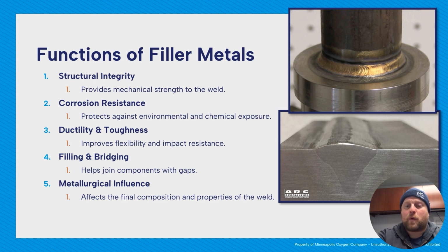Things like Cor-Ten or weathering steel, you have to use a particular type of filler to make sure that you are getting enough of a mix of the Cor-Ten and the filler so that the weld joint will corrode at the same rate as the base metal, like it's supposed to do. Because if you have Cor-Ten and then your joints all rust out, not really useful at all. So that's something to think about.